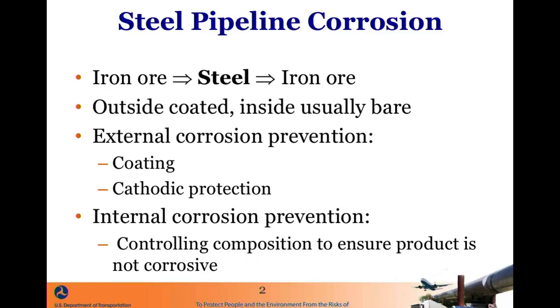And so we need to keep it away from oxygen so it doesn't go back from being steel to being rust again. And so we mainly do that by coating the pipeline on the outside. And the inside of the pipeline is usually bare because we can tightly control the pipe. Inside of the pipe is sealed from the outside. So on the outside of the pipe, we think about wet soil that could corrode the pipe. So we usually have a pipeline coating. It could be coal tar for old pipe. New pipe is usually fusion bonded epoxy, which is almost like melting plastic on the outside of the steel pipe.